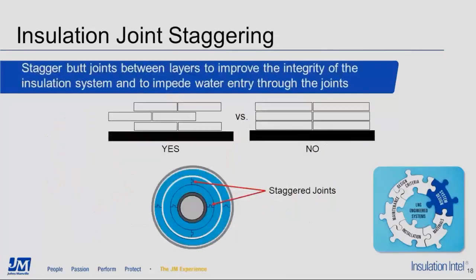The next key design decision is how the insulation joints will be staggered. This applies to both the circumferential or butt joints as well as the longitudinal joints. JM recommends that all joints between layers be staggered. In the top 2 pictures, you can see the recommended method for staggering the butt joints. Requiring the butt joints to be staggered in this manner between layers improves the integrity of the insulation system and impedes water and water vapor entry through these joints by forcing any water entering the insulation system to take a more tortuous path through these staggered joints.